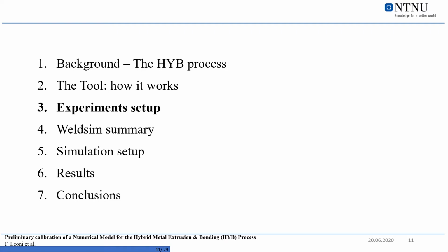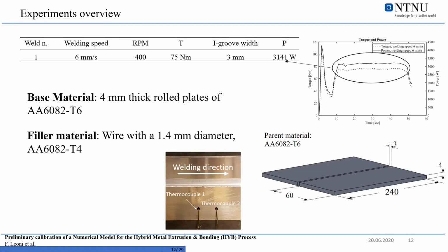have been carried out. So the experiment consisted in welding of aluminum alloy 6082 received in T6 condition, and the plates were 4 millimeters thick, and what was measured was the power consumed by the machine, and a couple of thermocouples were used, placed 3 and 4 millimeters far from the groove surface wall in order to obtain the temperature evolution in those points and to compare those with the simulation.